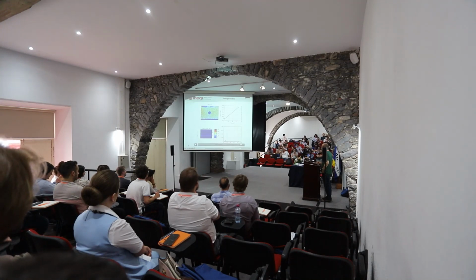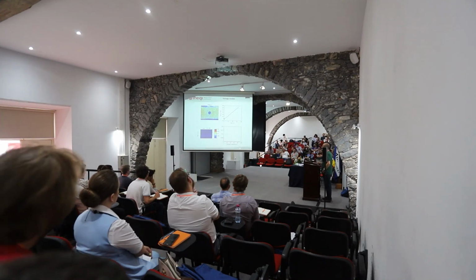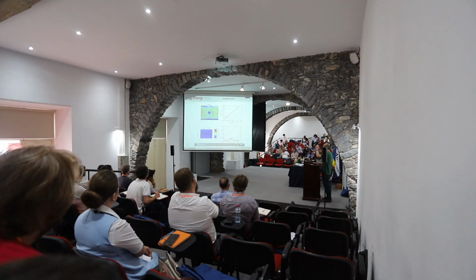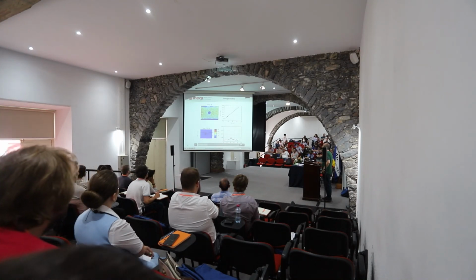I have plotted two lines there in red and in blue, and here you'll see the strain along these lines. All from digital image correlation, so no simulation there. So we'll start loading the specimen. You can see the strain concentration, of course, from the notch there. And then you keep loading. You can see the strain concentration, and here you get two cracks.